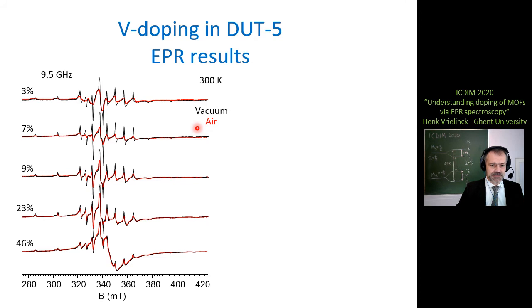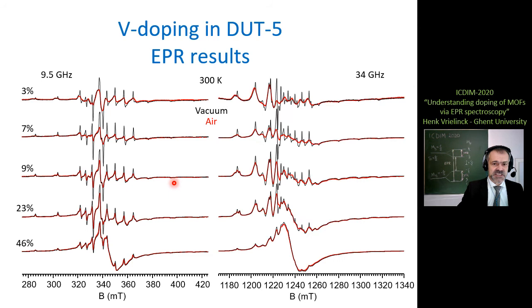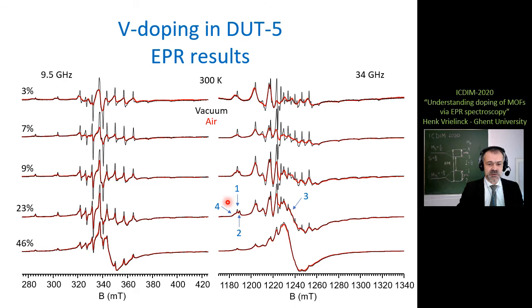We had to use different metal salts in this synthesis — in particular vanadium sulfate as doping salt. We made a concentration series of this MOF, and in the EPR spectra recorded at X-band at room temperature under vacuum and in air, we see that there is certainly a vanadium center present in this MOF whose EPR spectrum gets broadened when exposed to oxygen in air, like MIL-53 in the open pore state. However, it is also clear that in this framework this is not the only vanadium center present. The compositeness of the spectra is even clearer in Q-band, where we can recognize up to four EPR components. In the lower EPR line, which should be a single line if only one vanadium center were present, we can recognize up to three subcomponents. As the vanadium concentration rises, a broad background line develops.